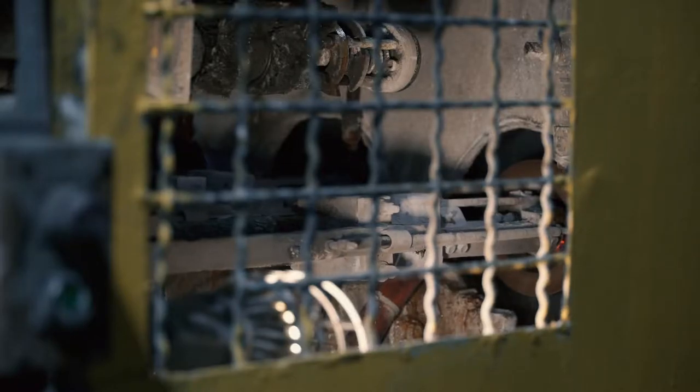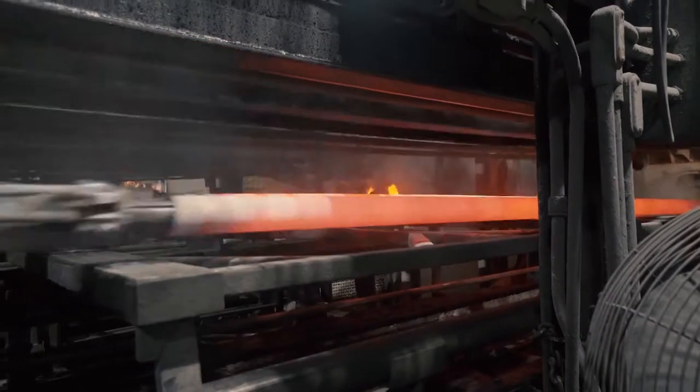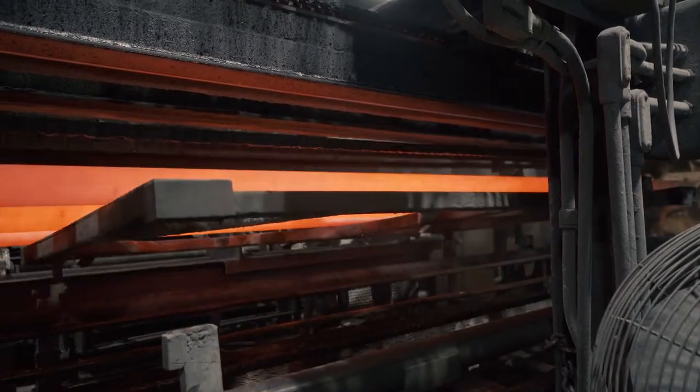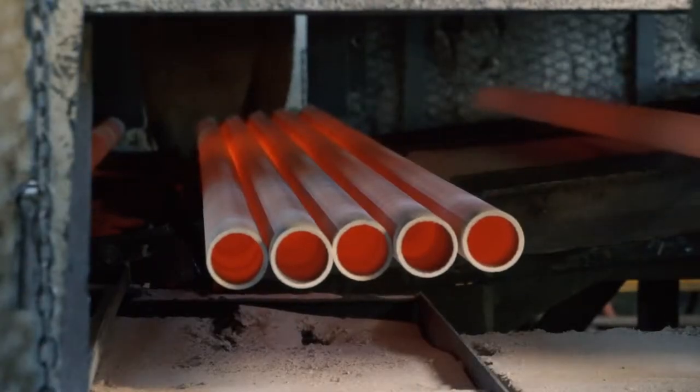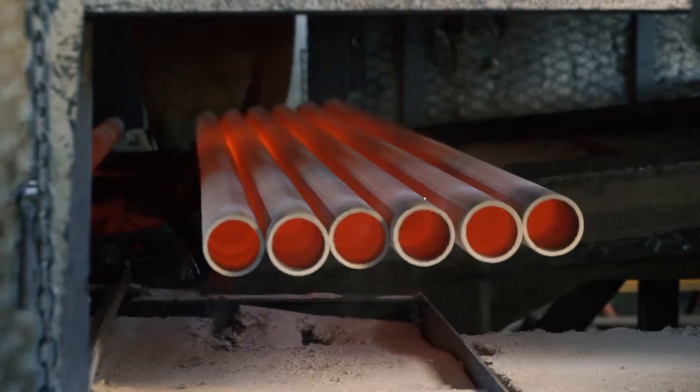In the beginning of the pipe casting process, slurry is injected into the pipe machine and spun at high speeds. A measured amount of molten iron is then poured from the boot into the pipe machine, which distributes the iron evenly to ensure uniform wall thickness of the pipe. Once fully formed, the white hot pipe is pulled from the machine and placed onto a conveyor for cooling and transporting to the pipe dip for finishing. This centrifugal pipe casting technology produces pipe of superior and consistent quality.